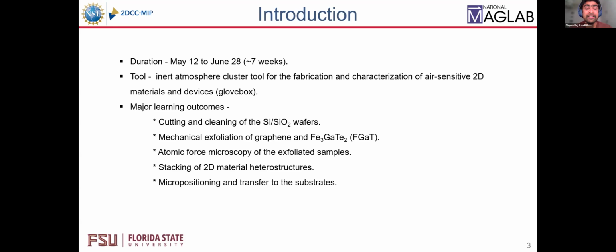So when I'm looking back, my major learning outcomes from this program was getting a basic understanding of the experimental techniques for device fabrication, starting from cutting and cleaning of silicon dioxide wafers, mechanical exfoliation of graphene and Fe3GaTe2 or FGaT, that is my material of interest, and doing atomic force microscopy of the exfoliated samples within the glove box, and stacking of different 2D material heterostructures, also micropositioning and transfer of the stacks to the desired substrate. In my case, it's an LTEM grid.